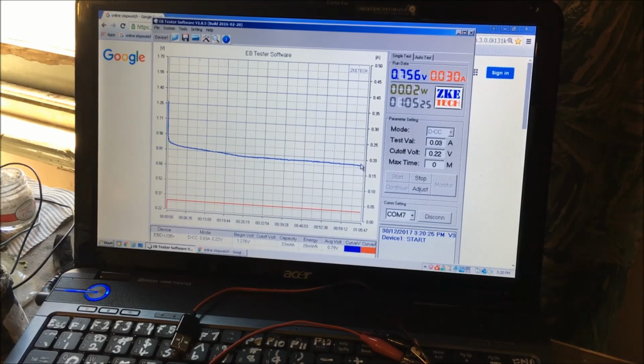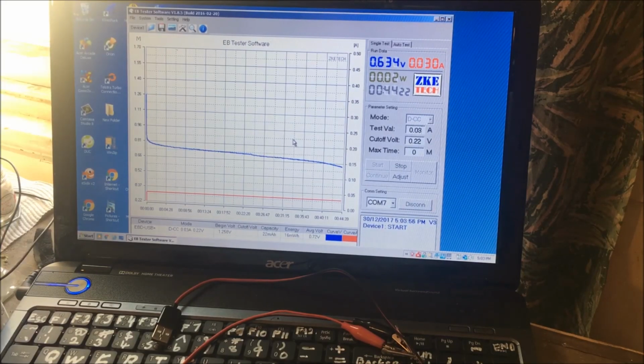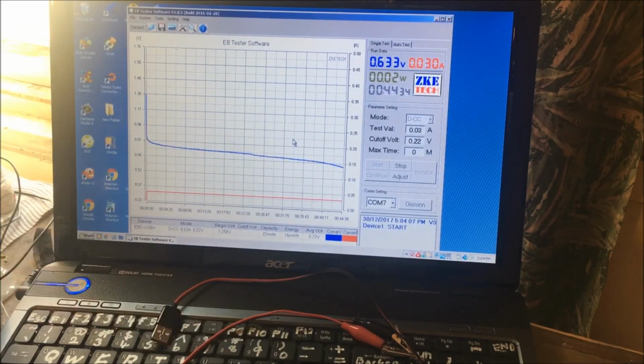Okay, I'll be back. Well, I replaced the electrolyte. I'm not sure if it was the replacing of the electrolyte or getting rid of the copper particles out of the electrolyte, which has done it. But it's 44 minutes run time, and we're at 0.6. And that's with the original carbon coated zinc cell and the carbon and copper graphite rod set electrode.